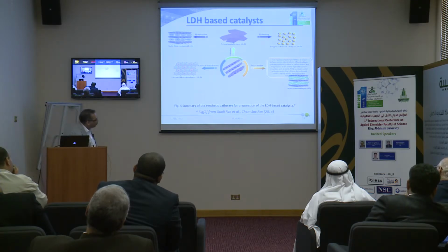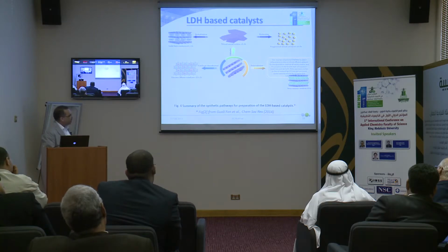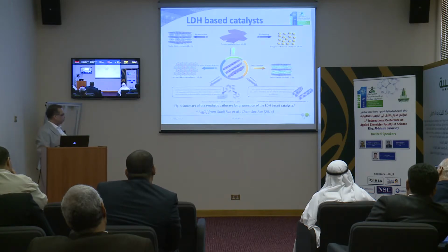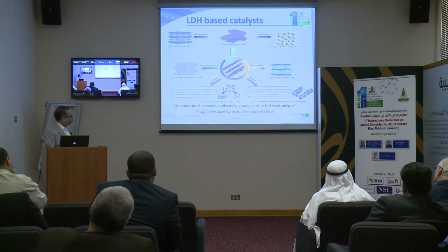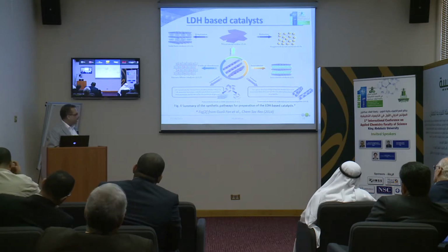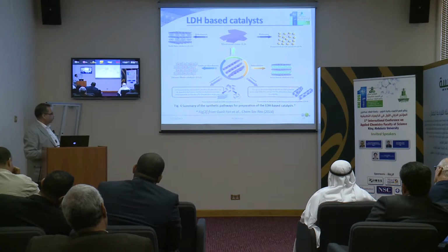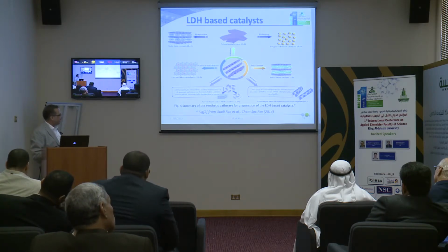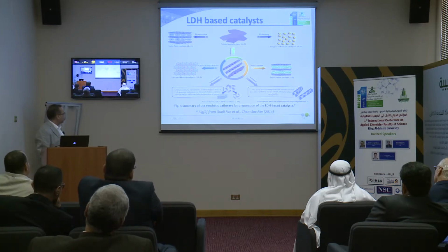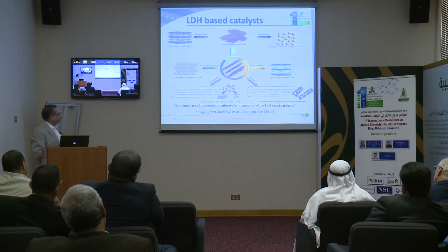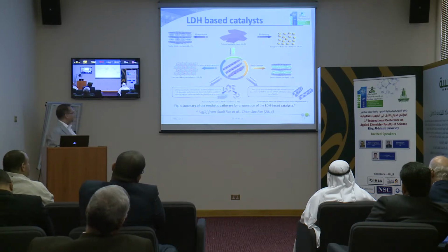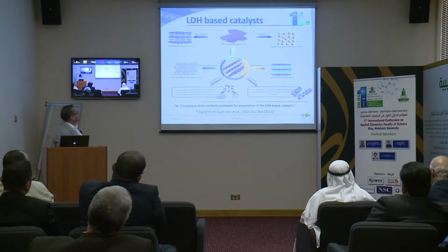Or we can completely remove the interlayer anions and replace them by DNA, polymer, whatever, and have other applications for the intercalated layered double hydroxide. Or, as our group, in collaboration with UCL London and Imperial College, supported the layered double hydroxide on graphene oxide and tested this smart material for CO2 absorption, and it found very good application as an absorbent. So graphene oxide improves the absorption capacity of the layered double hydroxide itself. Or you can do delamination of the material, and according to delamination you can have gold nanoparticles on the ultrathin film, which has very good performance in the oxidation of glucose.